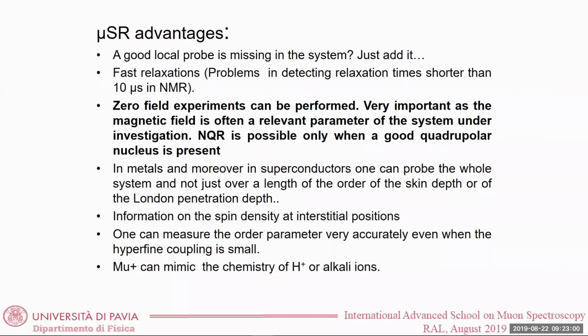Well, another relevant case where it is much more important to do MUSR, as I already mentioned in one of the first slides, is that you can do zero field experiments. And this is because you have already a fully spin polarized beam. While in the case of magnetic resonance, as nuclear magnetic resonance or ESR, you have to apply a magnetic field to generate your magnetization, which at the end will give you your signal.